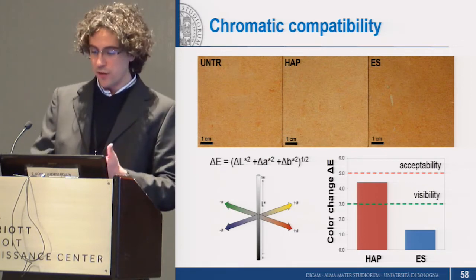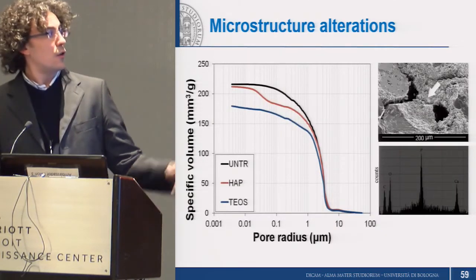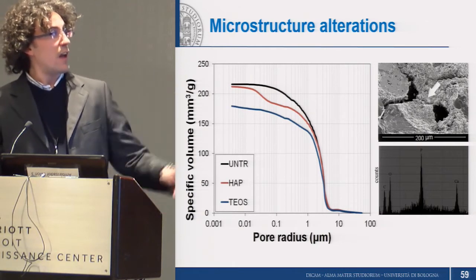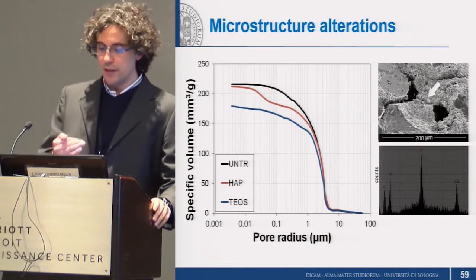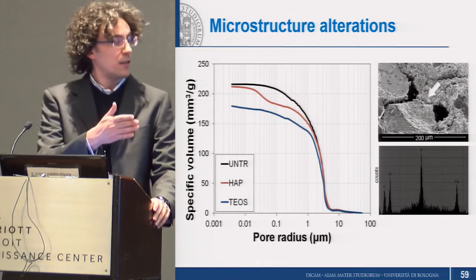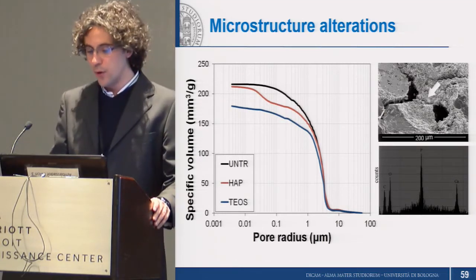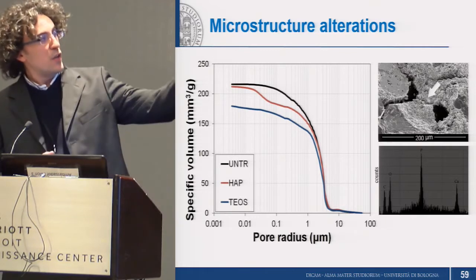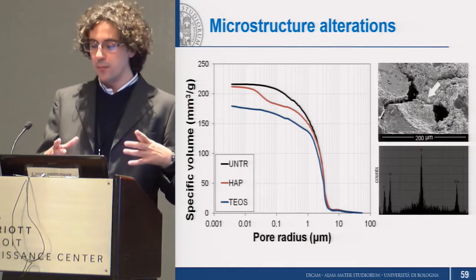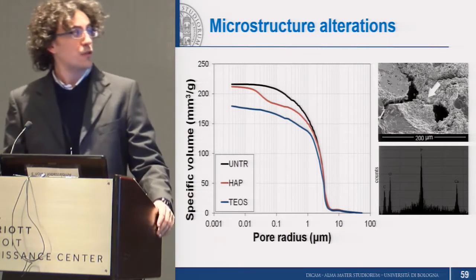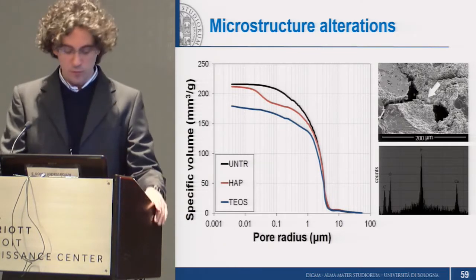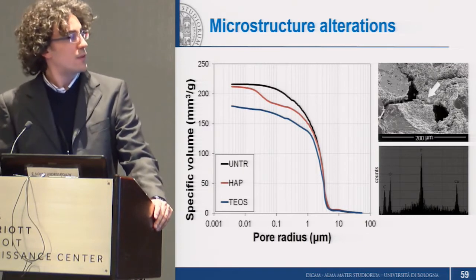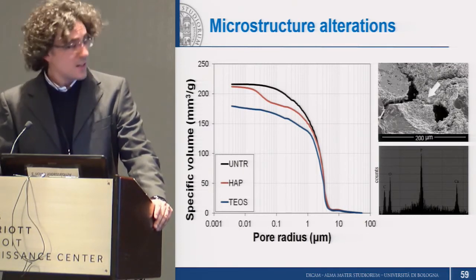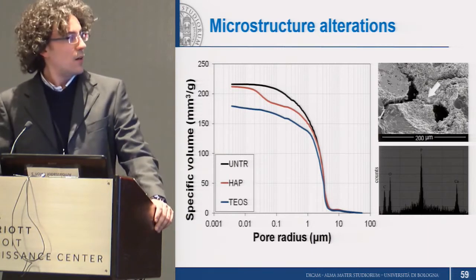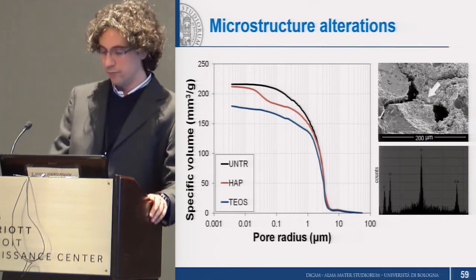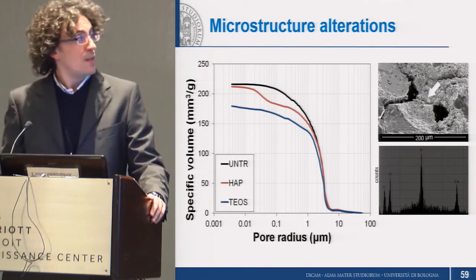And then coming to the alteration of the microstructure, as you can see, our HAP treatment in red only slightly reduces the total open porosity. However, it causes a shift towards smaller pores in a certain range. This is because, as you can see on the right, bigger pores were partially filled by our consolidant, so that two smaller pores were formed in place of our former one big pore. And in the case of TEOS, ethyl silicate, our alternative treatment, a more remarkable pore occlusion took place.